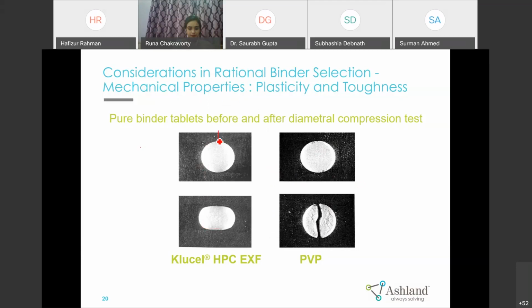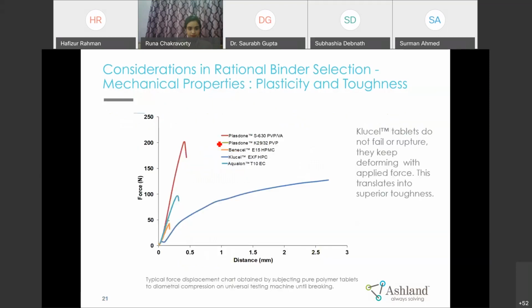So what we did, we compressed a tablet like we do in a hardness tester, right? We compressed from two sides, and because of this force, the tablet shape changed from round to capsule shape. Then we measured how much distance this tablet traveled without breaking. That distance we measured on the x-axis, in millimeters: 0.5, 1.5, and so on.